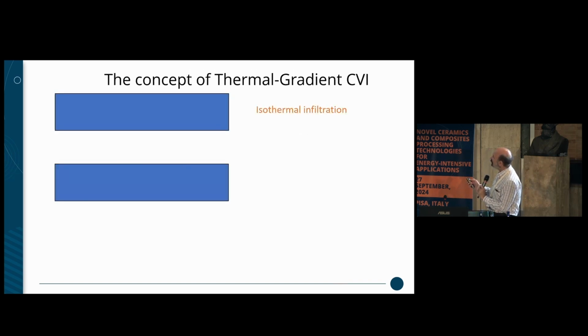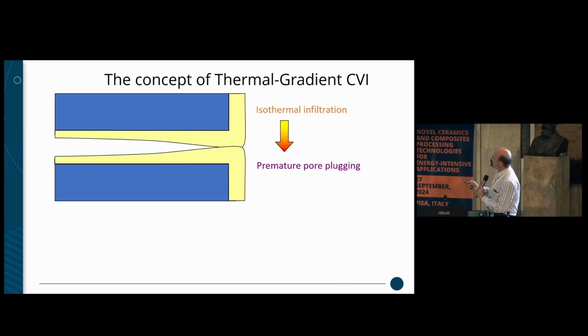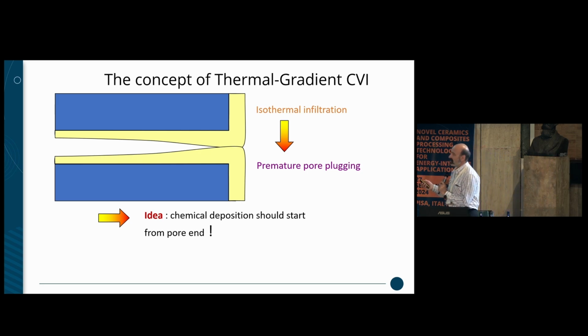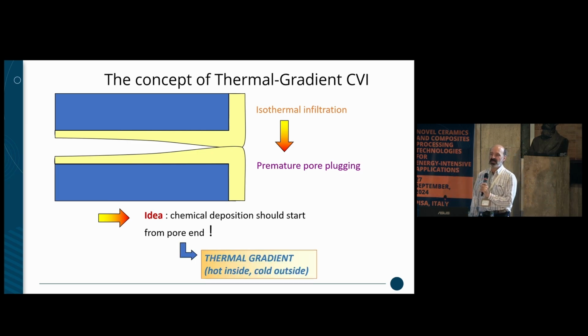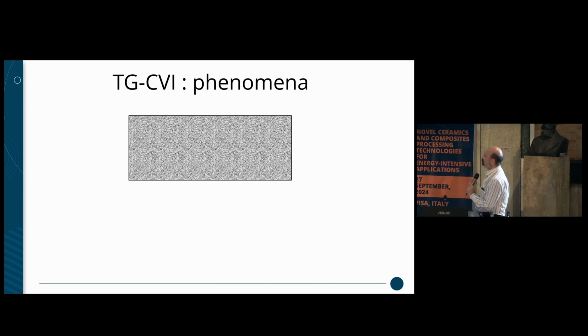Okay, so that's fine, but the problem is that isothermal infiltration leads to premature pore plugging. And the idea is that we should activate the chemical deposition rate in the end of the pore and not at the pore mouth. So how to do that? Of course, the idea is to apply a thermal gradient, hot inside, cold outside. So if you do so, you have heat going from one side to the other, so thermal gradient.